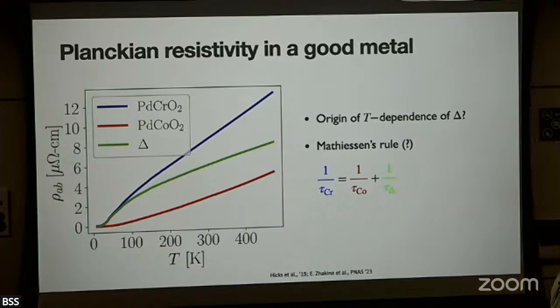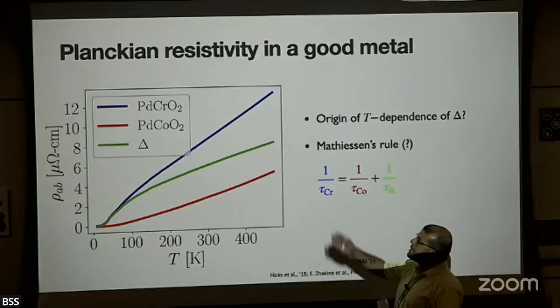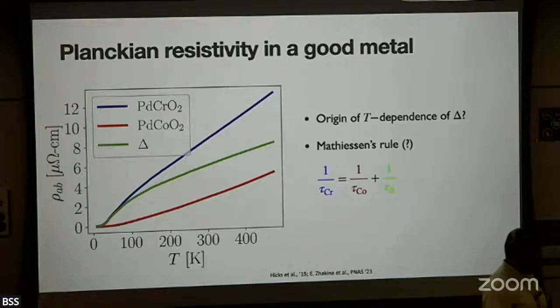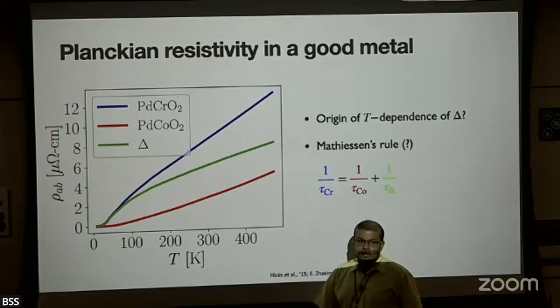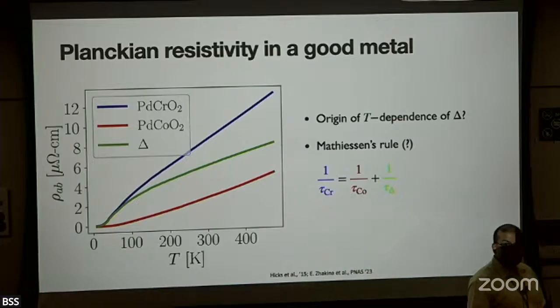Okay, now if you believe that you understand palladium chromium oxide essentially as palladium cobalt oxide plus some other scattering mechanisms via some Matthiessen-type rule, then the green curve is the difference between the two scattering rates. So it's whatever would arise because of the difference in their ionic masses. Because the structure is the same, it's just instead of chromium, you have cobalt.